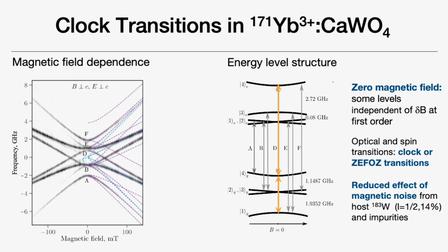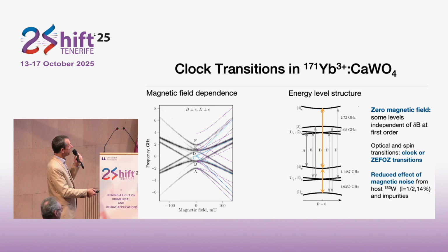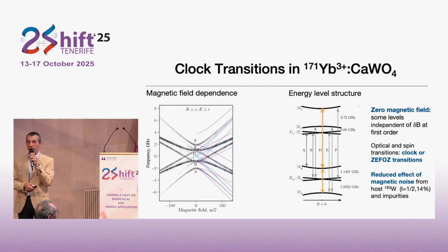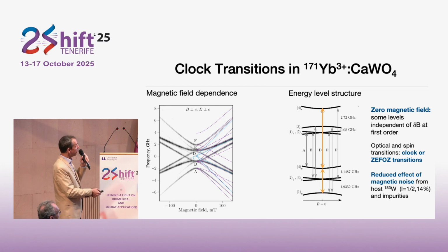The ones corresponding to ytterbium-171 are shown in this purple color here. The blue lines actually come from ytterbium-174. It's an impurity of the original material we used, which is isotopically enriched in ytterbium-171, but there is still 5% of ytterbium-174, and we also see the transitions corresponding to this isotope. But of course, we are not interested in these properties. So from the simulation of these spectra under magnetic field, we can end up with the energy level structures that you can see here. So three levels in the ground state, 3 levels in the excited state at zero magnetic field. But now what is interesting is to see what happens if we have small magnetic field fluctuations around this B equals 0 condition.